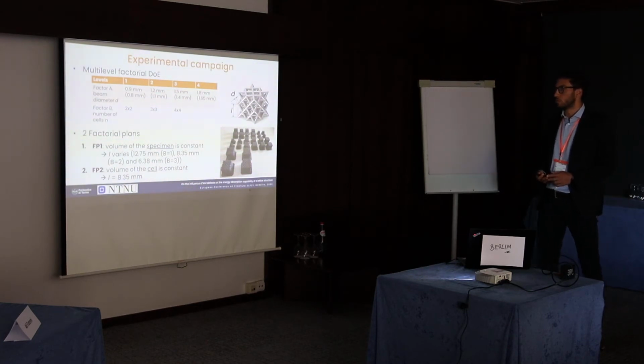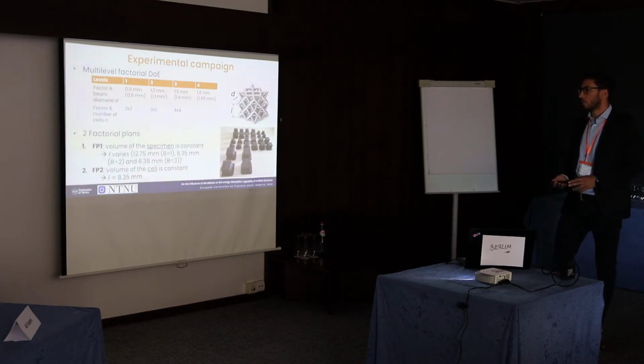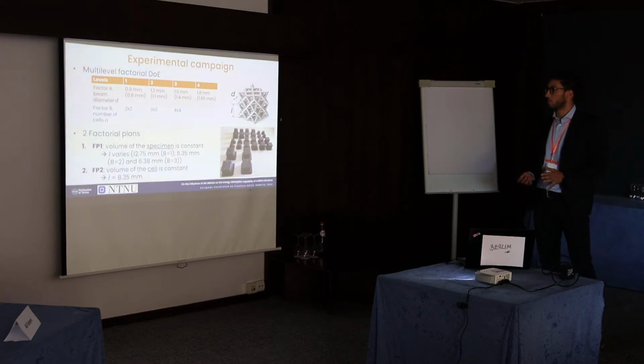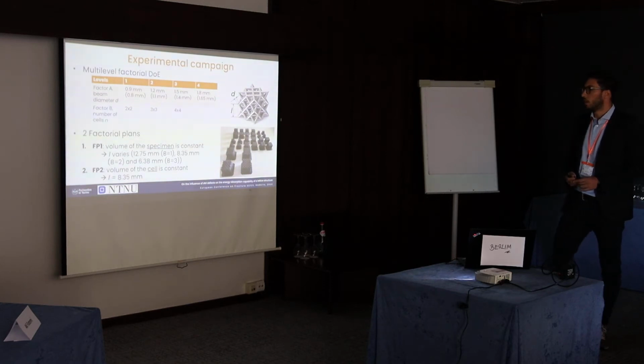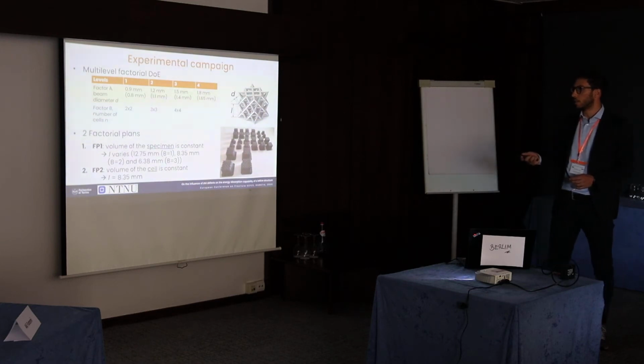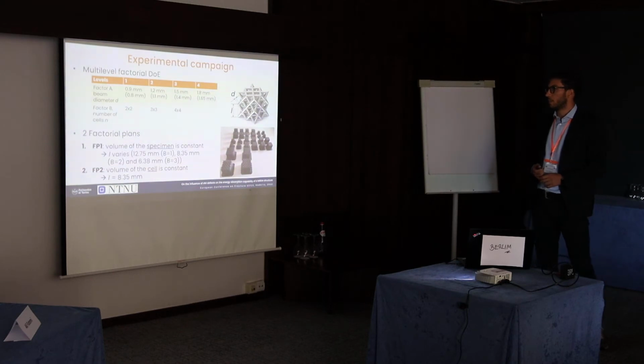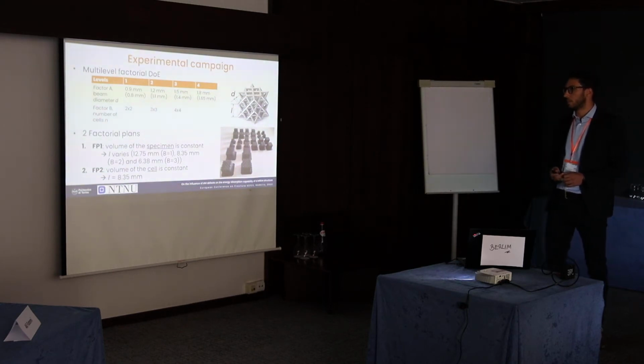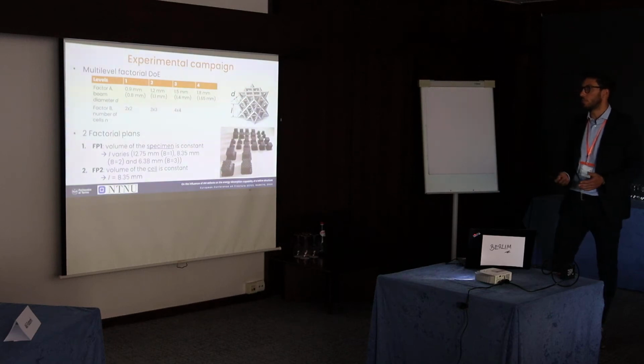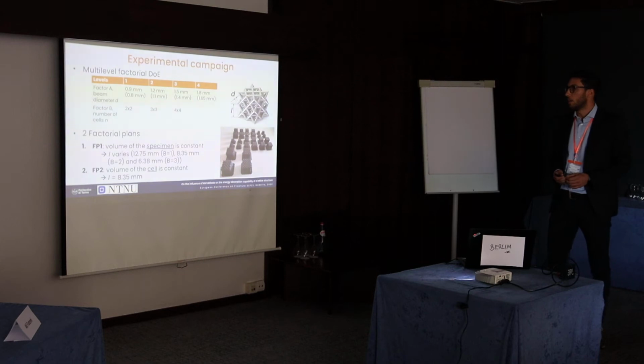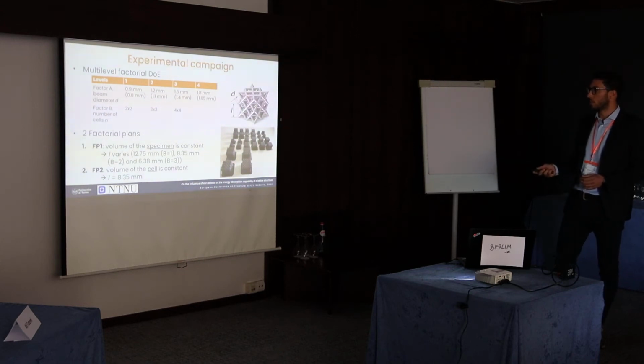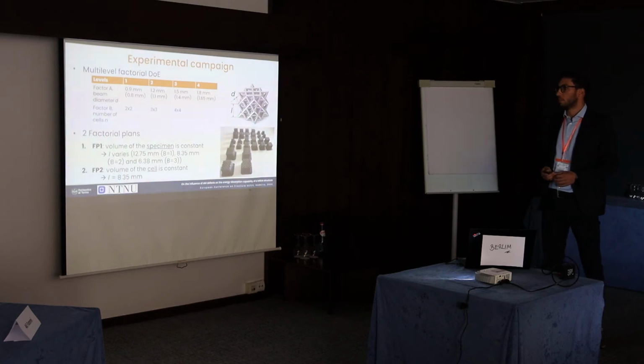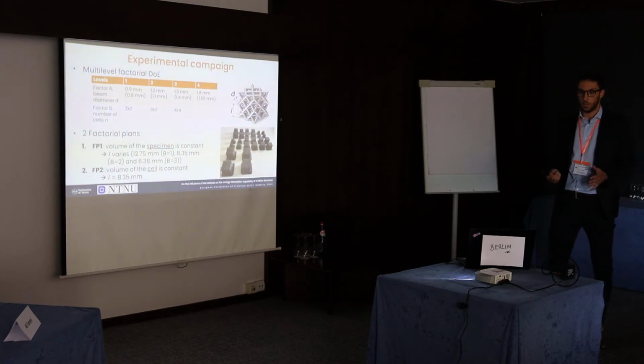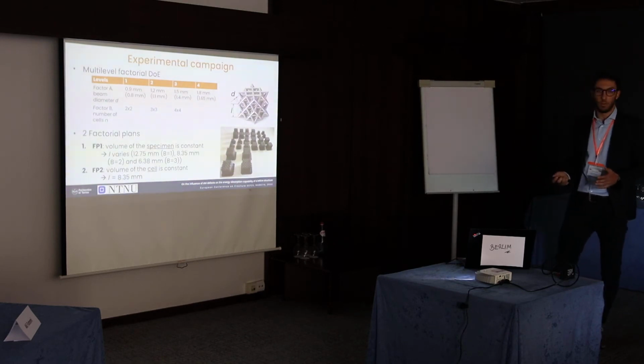And in particular, we performed two factorial plans. In the first one, we investigated the effect of two geometrical parameters, the diameter d and the size of the unit cell, the length L. In particular, according to the factorial plan, increasing the level, the size of L decreases. And in the second factorial plan, instead, we investigated the effect of the number of cells that we consider in a specimen. So we kept the size of the unit cell, L, constant, and we varied the number of cells considering different replications of the cells, so 2 by 2, 3 by 3, or 4 by 4 replications.